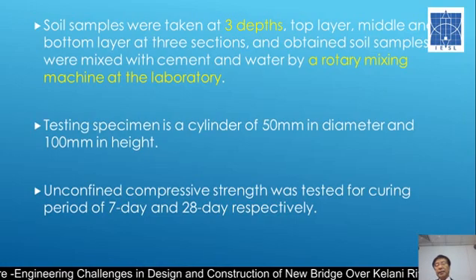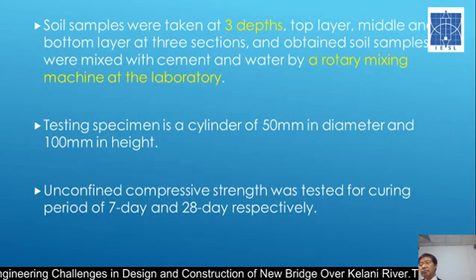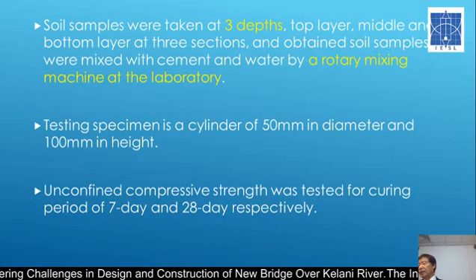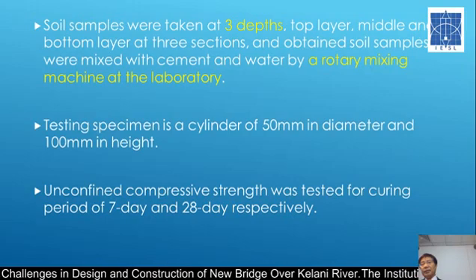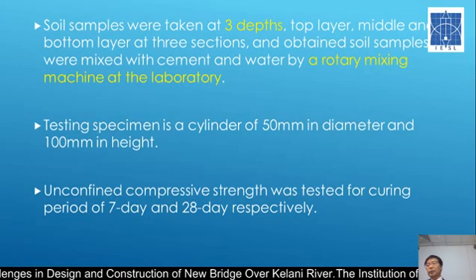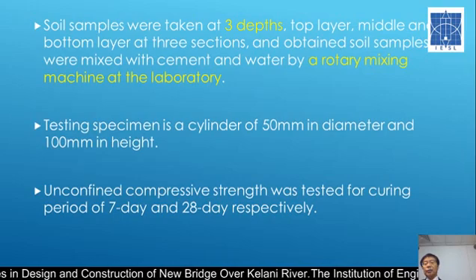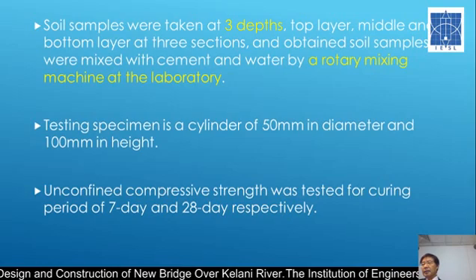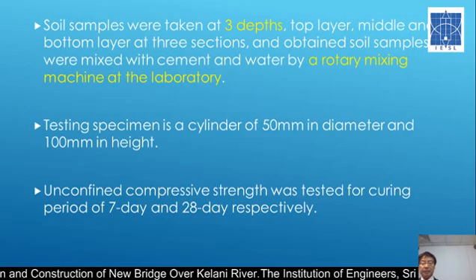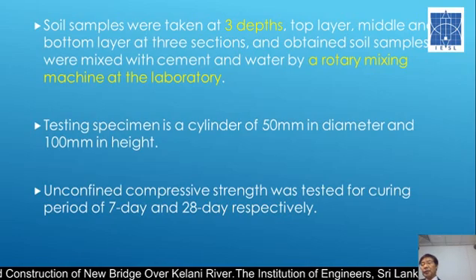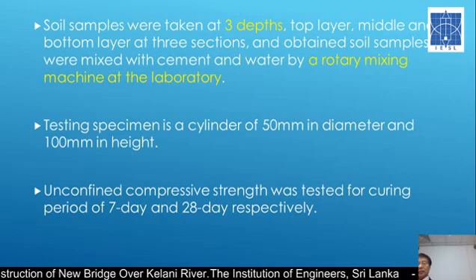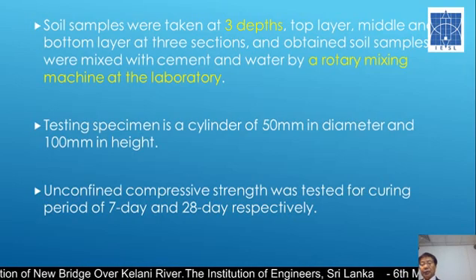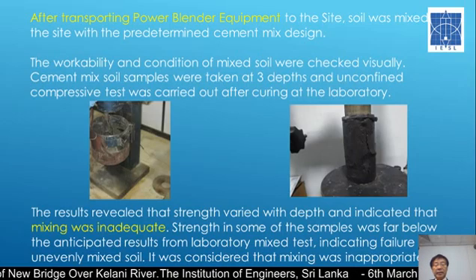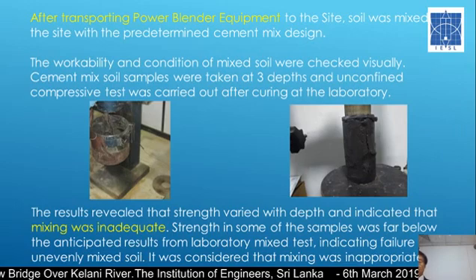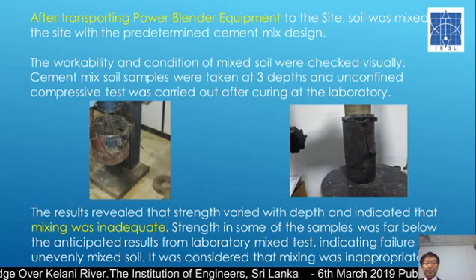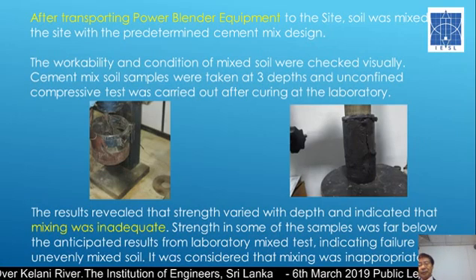And before we do that, to determine the design, meaning the amount of cement, the water cement ratio, and so on, we have to do some laboratory testing. We took the soil from the actual site and did manual rotary mixing at the laboratory. And we tested the improved soil by compression test, for 7 days or 28 days. So these are the failures. The left-hand side is a mixture of the soil mixed manually, and the right-hand side is a failure of the soil column. With this, we had a very good strength,